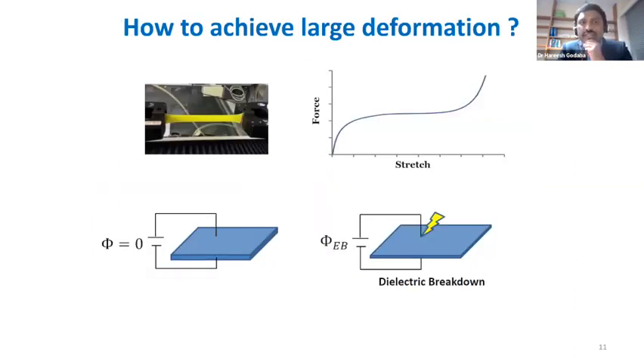So I would like to discuss a bit on some of the efforts that I've been a part of in trying to achieve large voltage-induced deformation in these elastomers. Okay, so as you can see here, we know that if you take an elastomer, or basically a natural rubber membrane, and we stretch it, the force-stretch curve looks like this. Initially it is stiff, then the polymer has some softening behavior, and finally when we are close to the stretch limit, it will be very stiff like this. And the failure is basically accounted by wherever the tensile strength of this material is, right? Or the rupture stress, once that is reached, there'll be a rupture.